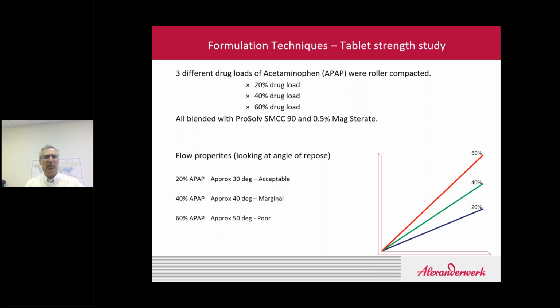We took a look at the angle of repose of each one of these particular blends. And it was interesting to see the higher the loading of the APAP material, the poorer the material flowed, which really wasn't too surprising actually, because the APAP material is very, very fine and doesn't have flow qualities that are good at all in the beginning. So at a smaller drug loading of 20%, we had approximately a 30-degree angle of repose in the material. At a higher drug loading of about 40%, the material still flowed. It was marginal. It was about a 40-degree angle of repose. But when you got to the 60% APAP drug loading, the material really didn't want to flow whatsoever. It was a poor flow and it was about 50 degrees.